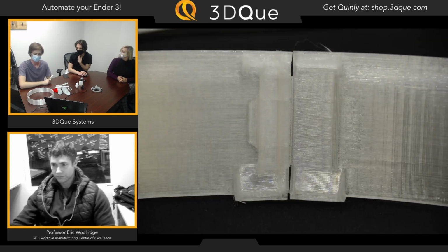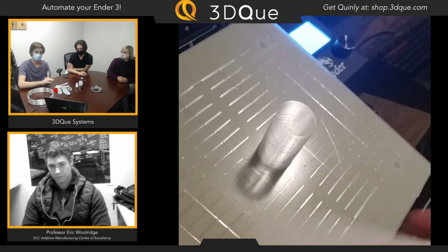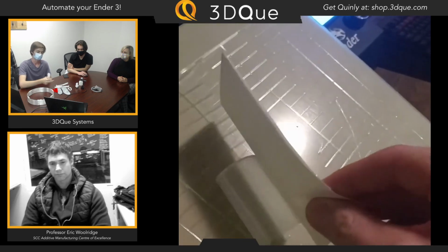And yeah, the polycarbonate stuck down really well during printing, and it released very nicely actually. While it cools down, you can actually hear the part cracking and kind of falling off the bed even a little bit. At about 60 degrees Celsius, it just completely detaches. And you can see a picture here of me just wafting a piece of paper and everything just falls right off.